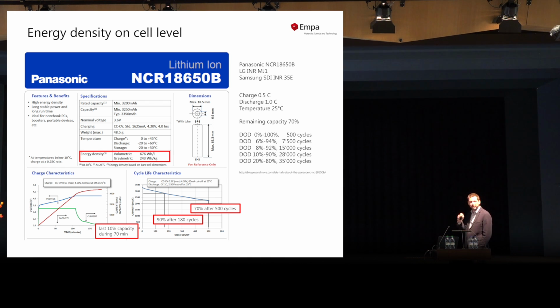So the batteries don't maintain this high energy density over the battery lifetime. You can see here the cycling life. After 500 cycles, the battery is down to 70% of its initial capacity. And Tesla drivers are always shocked when I tell them that after 500 cycles, your battery is down by 70%. That's not fully true, because what Tesla is doing, they're limiting the range of charge and discharge. And you can see this here. When you limit, for example, the depth of discharge from 6 to 94%, you can extend significantly the lifetime of the battery. So that's a trick that everybody's using, which makes it also very difficult to compare different battery products from different manufacturers and put them on the same level, because it depends very much on the history and how the battery is cycled.